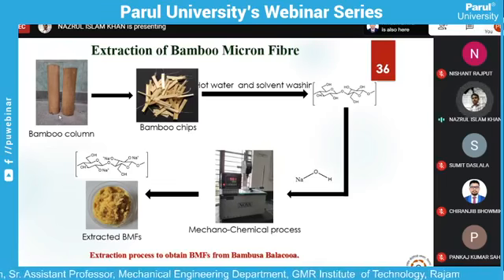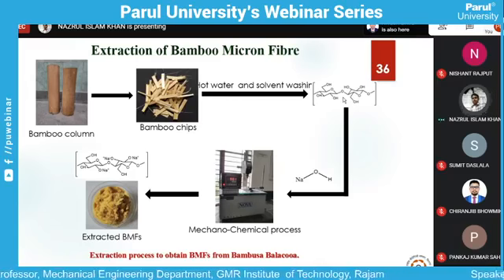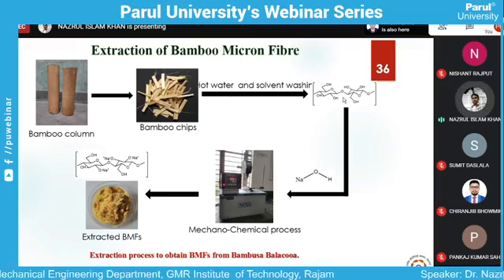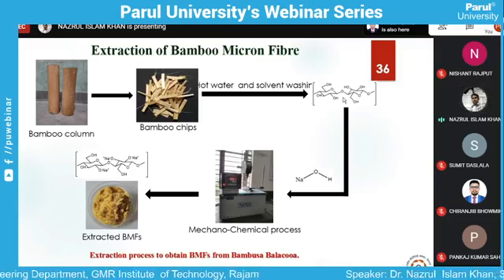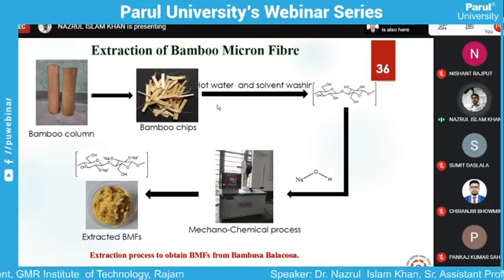Actually, bamboo itself is a matrix, a composite, having cellulose as the fiber and lignin as the matrix. Once we do the alkali treatment, the matrix material gets removed and only the fiber can be extracted.